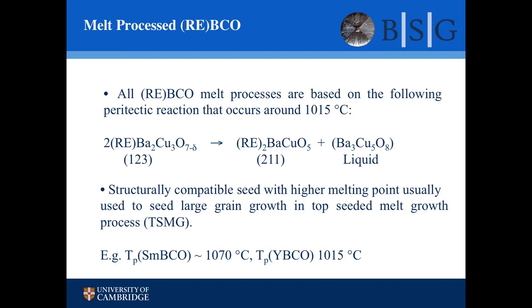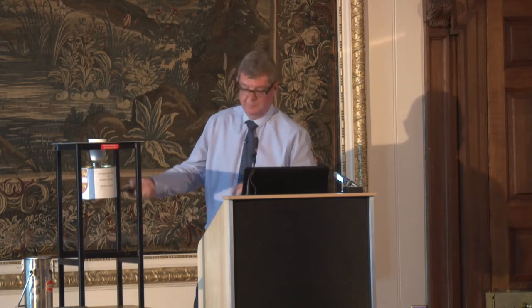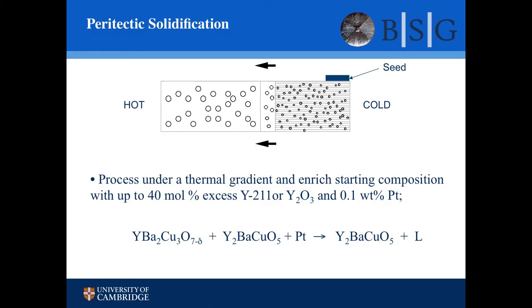And essentially what you do is you just reverse this reaction, you partially decompose your material, you add a structurally compatible seed, and then you cool it back down slowly. You nucleate and grow at the position of this seed. And conveniently, we can substitute yttrium for samarium, samarium barium copper oxide. It's chemically compatible, but it's got a higher decomposition temperature. So we don't melt the seed, but we partially melt the material. So schematically, this is what's happening.